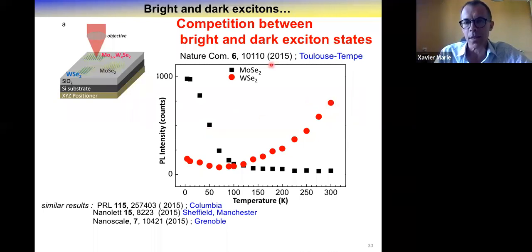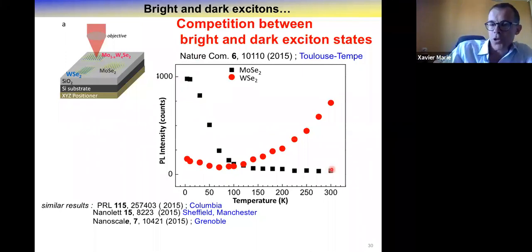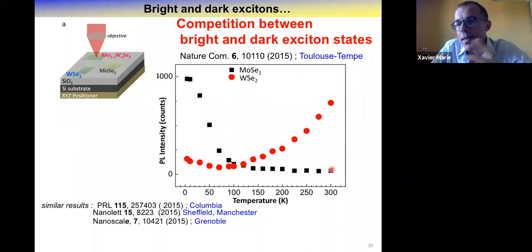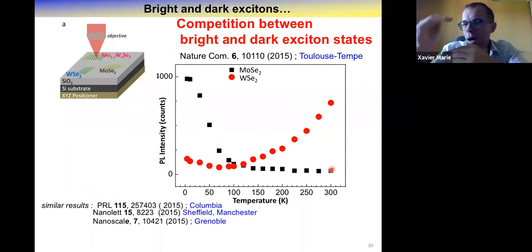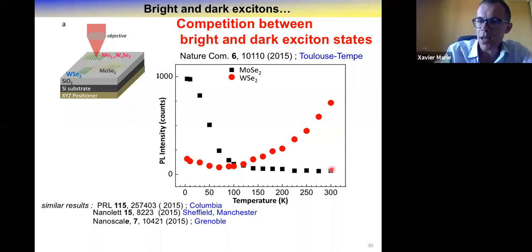luminescence intensity. Whereas in black, this is MoSe2, where you expect the reverse behavior, because bright and dark states are expected to be reversed. And indeed, you find the classical behavior of a semiconductor, a larger luminescence intensity at low temperature compared to room temperature. But it turns out that with this kind of experiment, it is difficult to really extract the energy between the bright and dark states with this kind of approach.